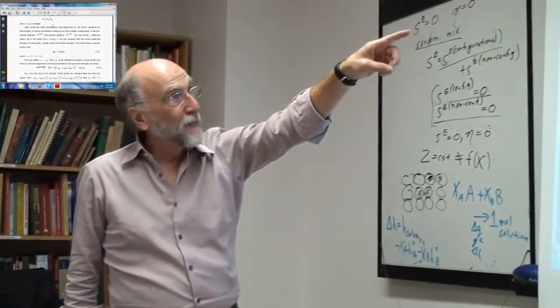Okay. I've actually seen the thing derived in terms of only the first nearest neighbors, and it says you're making the assumption that only first nearest neighbor pairs contribute to the delta H. Well, no, all the pairs can contribute, and it all gives you the same energy form. So there you go. Now that was to give me omega for the heat.